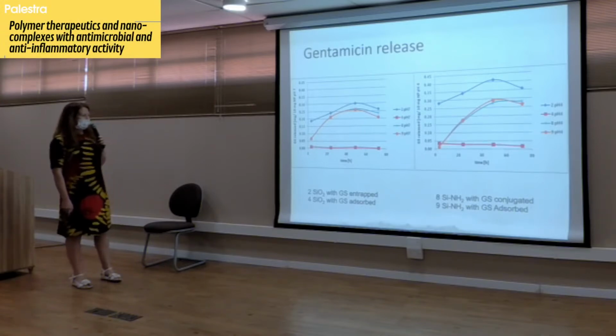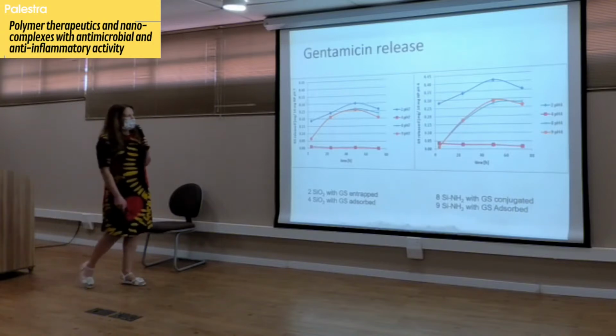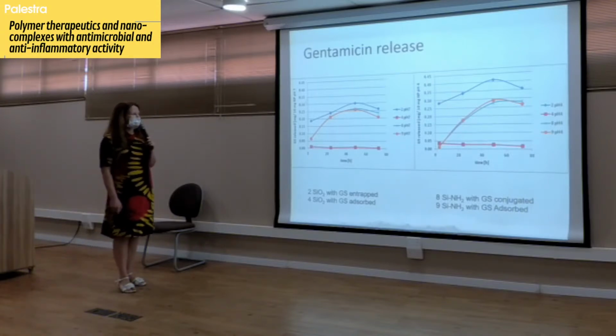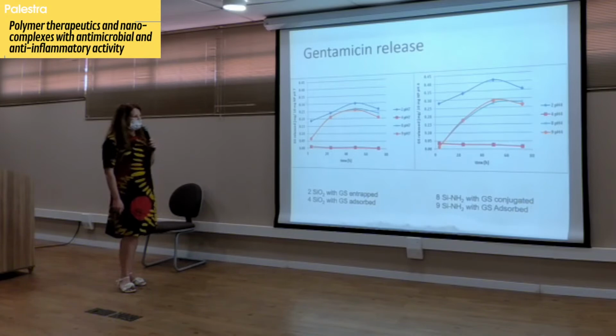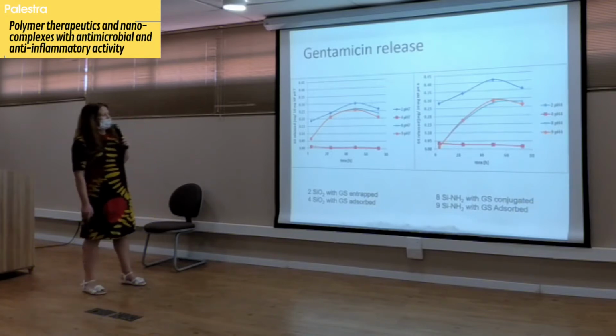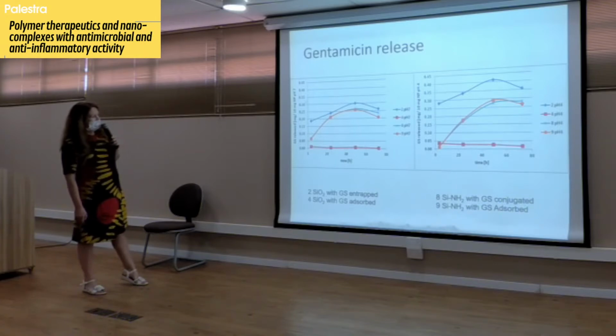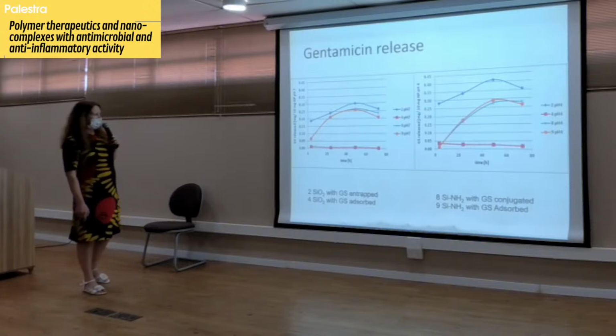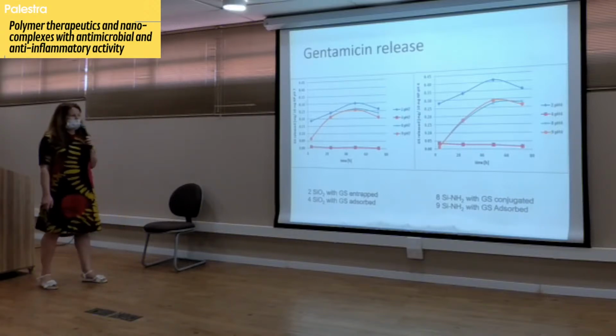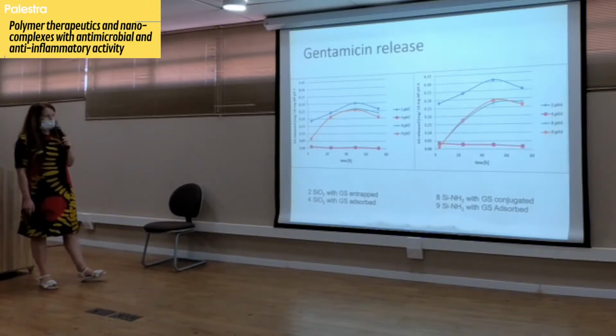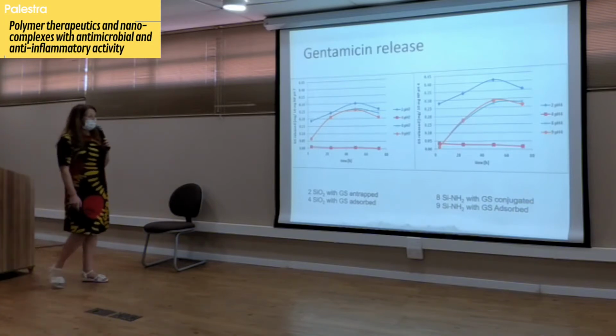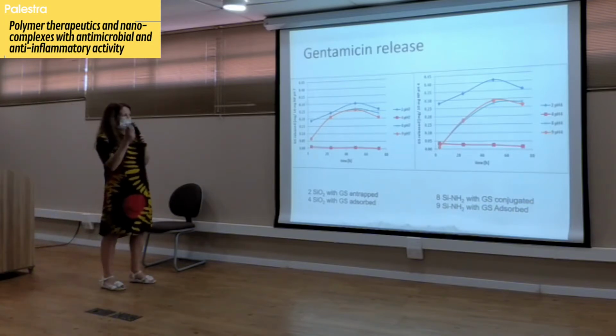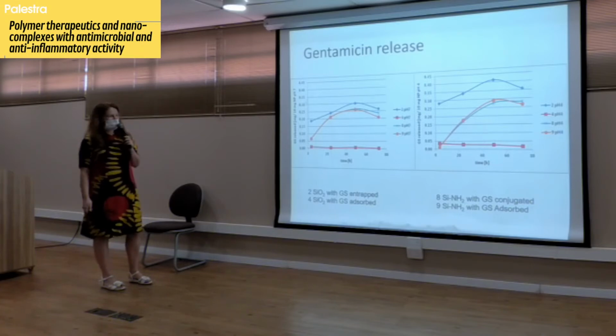And as you can see here, you have controlled release for a few days when you have conjugation, and when you have entrapment in the presence of suberic acid. When you have just adsorption, you do not really have that much release. Well, you have release, but it just happens in the beginning, and after this it goes to a plateau.